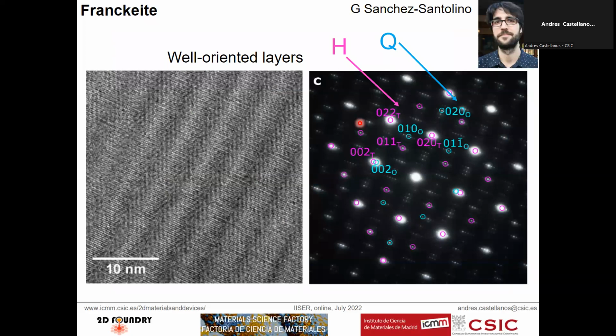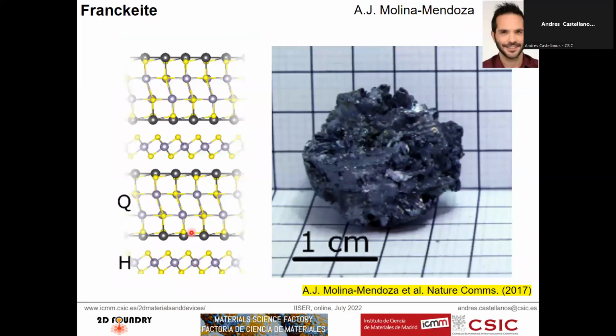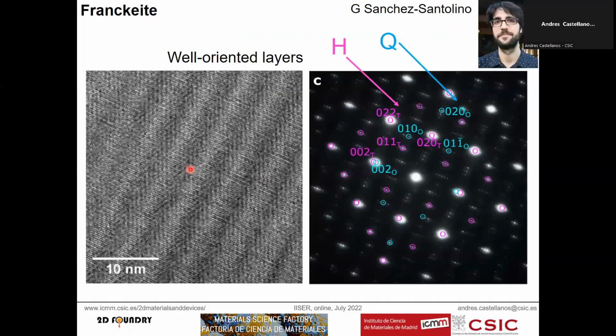And one of the first things that we did was trying to reproduce these TEM studies from the 80s. So we transferred this Franckeite onto TEM grids. And what we saw is this characteristic ripple pattern that happens in Franckeite. And when you do electron diffraction studies, you see that you can resolve the H and Q lattices, that they are these H and Q lattices here. So you can indeed resolve it.